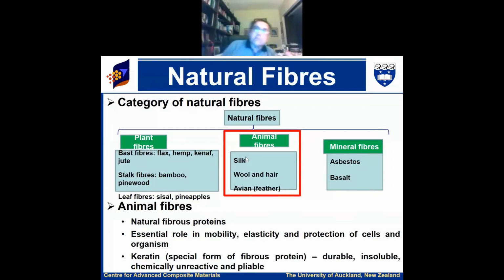Now, plant fibers themselves are combustible. So people use that. You will never be successful if you have those plant fibers in the composite materials. But quite surprisingly, you see that peak heat release rate, rather than going up, gets a drop. Total heat release, the area under the curve, more or less remains the same, but the peak heat release rate gets a drop. I think it is because the fibers themselves are not conducting material, so the flux has to go around. I don't know, because I have not seen any analysis of that, but this is a conjecture.